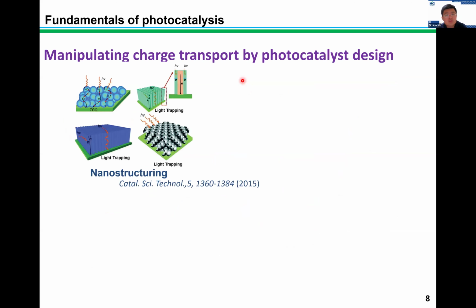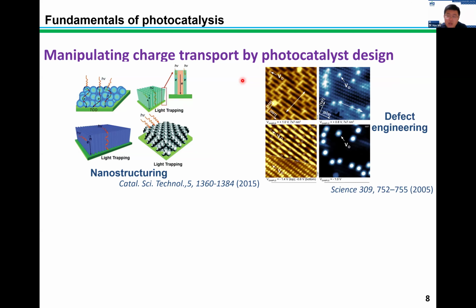For example, we can nanostructure our semiconductors. We can make them into one-dimensional nanorods, two-dimensional nanosheets, or three-dimensional ordered macropore structures. With this unique structure, we can improve the light scattering effect and also facilitate spatial charge separation. Meanwhile, we can also intentionally induce defects on the surface of our semiconductors. Unlike other processes where defects are not desirable and we prefer the perfect lattice, in photoelectrocatalysis, sometimes defects can be beneficial. They can promote the surface and solid interaction and also extend the carrier lifetime of photo-induced electrons, which can have sufficient time to react with the reactants.